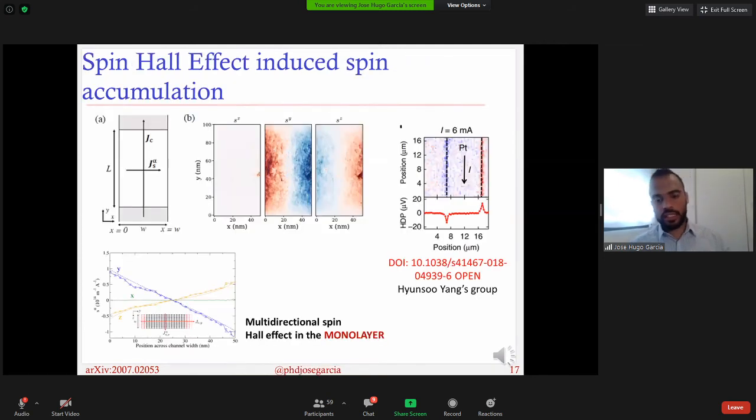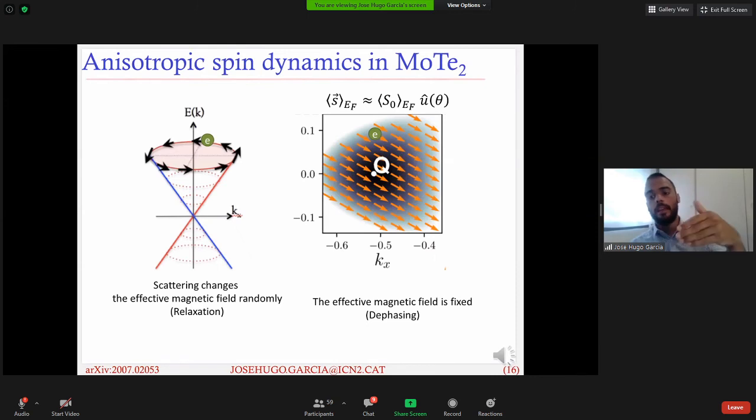In this particular case, you see that the spin texture is pointing primarily in the y direction. It's basically y and z like this. Because it's aligned, or mostly aligned, in the y direction, when you put the spin along that direction, the spin survives more. And because this is the YZ plane, when you put the electrons in the X direction, it relaxes immediately because it feels a completely perpendicular magnetic field.